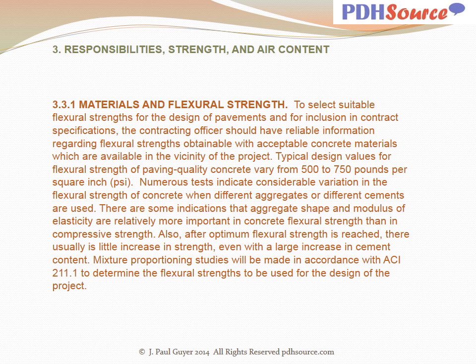Typical design values for flexural strength of paving quality concrete vary from 500 to 750 pounds per square inch. Numerous tests indicate considerable variation in the flexural strength of concrete when different aggregates or different cements are used. There are some indications that aggregate shape and modulus of elasticity are relatively more important in concrete flexural strength than in compressive strength. Also, after optimum flexural strength is reached, there usually is little increase in strength, even with a large increase in cement content.